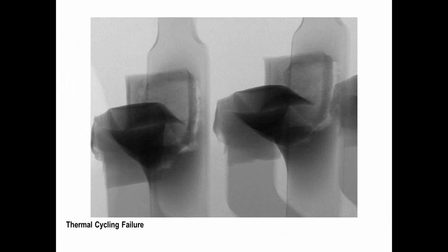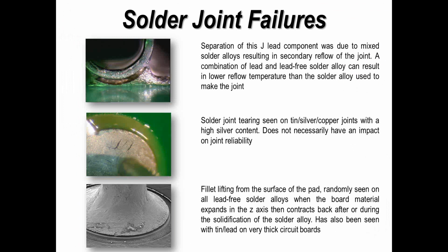Again, it's not uncommon to fill completely underneath SO packages, but you need to know what material you're using and the thermal expansion coefficient of the material for any conformal coating application. Generally speaking, as people tend to move more to spray coating, selective application, as opposed to dip coating, you tend to get less material. So consequently, perhaps this would be less of an issue if you were using those processes as opposed to dip, but you must always check the conformal coating material you're using.